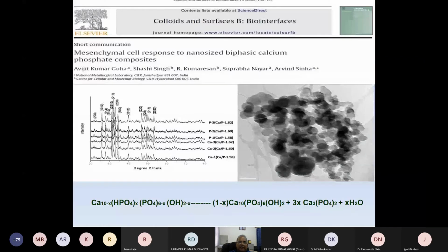In the next experiment, we changed the chemistry. We changed the chemistry of hydroxyapatite. We produced a calcium deficient hydroxyapatite. The hydroxyapatite formula is Ca10(PO4)6(OH)2. We produce Ca10-x in PVA matrix. And once it's precipitated, we decompose it into a two-phase material. One is hydroxyapatite, second is beta calcium phosphate.